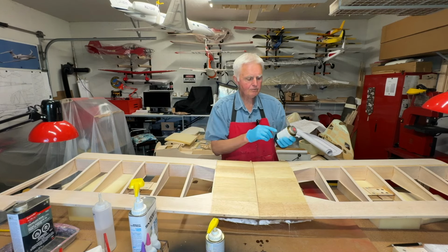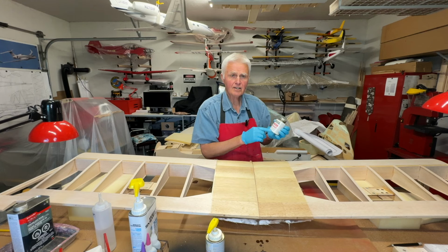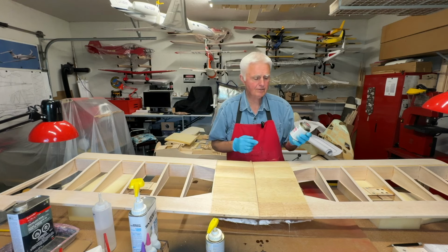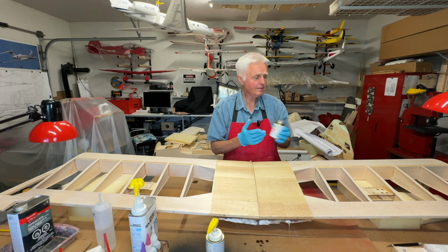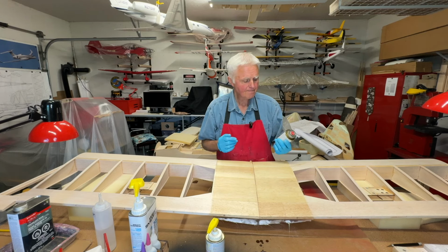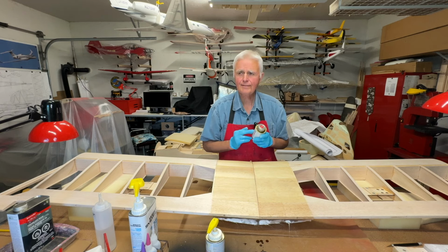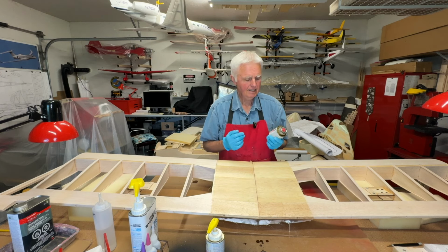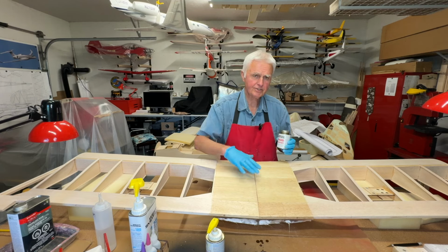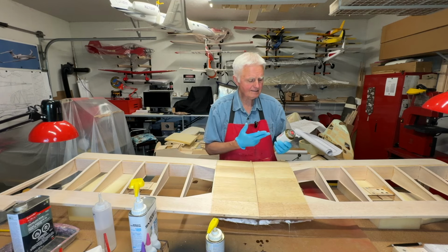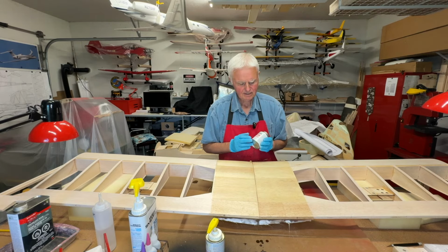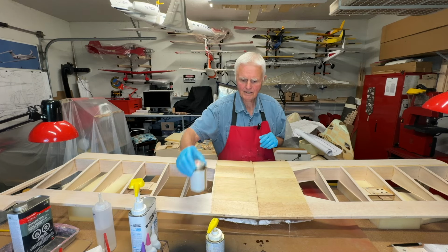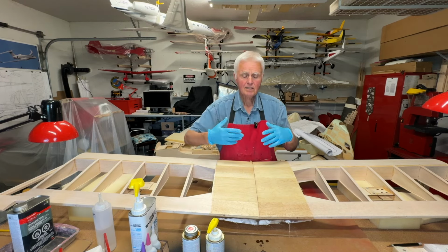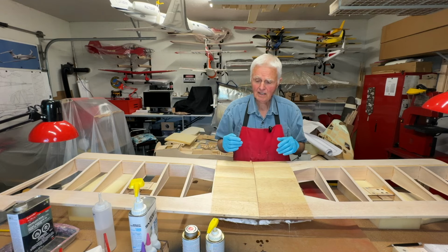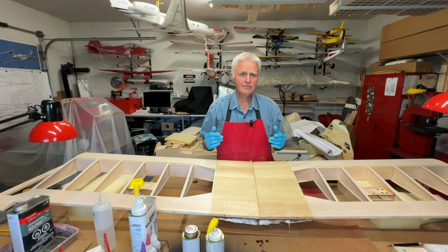They also make one which is called the fast hardener, and it's referred to as 205. I actually use this more times than not for anything of the smaller projects. This has a pot life of about 9 to 12 minutes, though you can work with it longer once you start applying it. It takes about 6 to 8 hours to cure. So it's definitely faster if time is important to you. If you need to clean up, or even if you like to thin it out, I use lacquer, which works really well. You could use acetone as well.